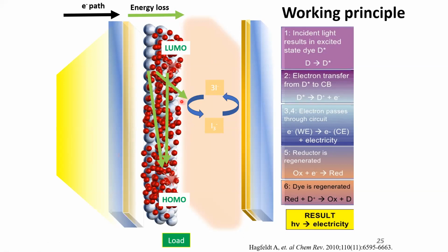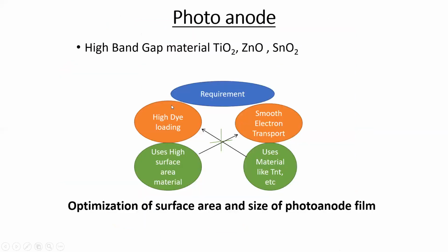So these are some recombination losses which reduce the efficiency, and we have to work around this problem. While fabricating cells, we should have better quality cells so that these recombination losses do not occur. In a solar cell, whatever wide band material we use, we should have high dye loading. As I explained, if dye loading is high, then light absorption will be high. And we should also have smooth electron transport so that recombination losses do not occur.